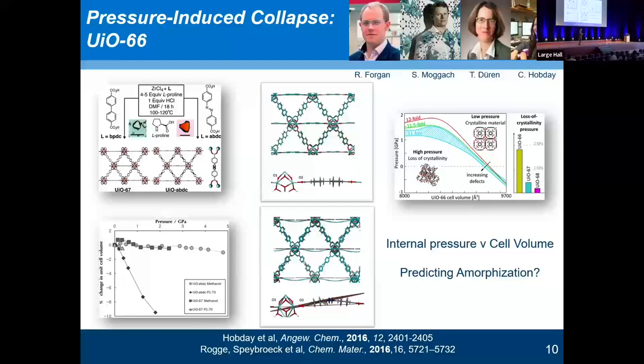Our own work has been on the UiO-66 systems and again, treating them as materials. You know, when do they collapse and what can we do about their collapse? Okay, what opportunities does it have? So in these UiO-66 materials, and this is with Ross Forgan, Stephen Moggach, Tina Düren, and Claire Hobday, Ross synthesized a UiO-67 material with a planar linker, and then also this functionalized equivalent, this azobenzene dicarboxylate. The average crystal structures look about the same. They're in gray here from a single crystal. You can see that it's a planar linker between the nodes. But when you do some MD simulations and take a snapshot, the UiO-67 linker is absolutely planar. That for that azobenzene one is not, though, it lies out of the plane.